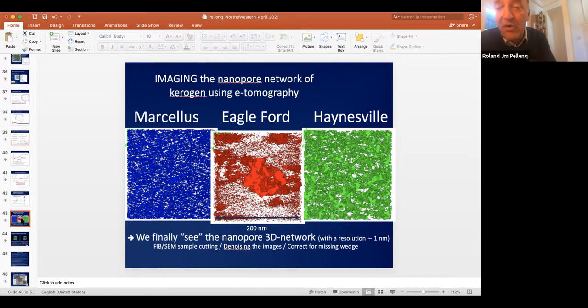That was my mind-blowing moment, because we were able to see nanopores, at the scale of 1 nanometer. That's really the thing. And you can see the connectivity, because once you have the image in 3D, you can start analyzing the pore size, the topology of the pore network, the way the pores are actually connected or not. And we found that, okay, immature kerogen is not so good because you may have big pores, fine, but they are not very much connected.